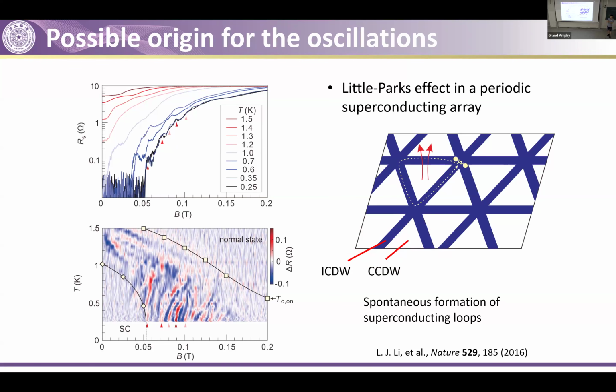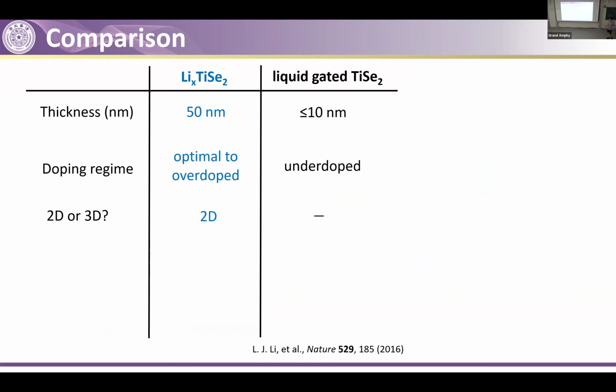This is not just one single commensurate charge density wave puddle. This is actually a big puddle. And around these CCDW domains, we then have the superconducting networks. And that sort of explains why we have this structure appearing in our system.